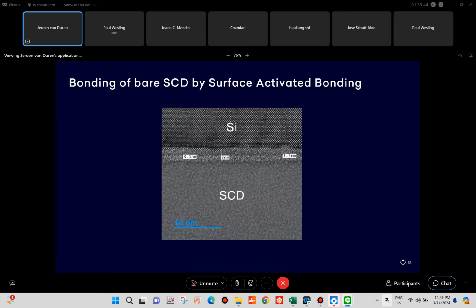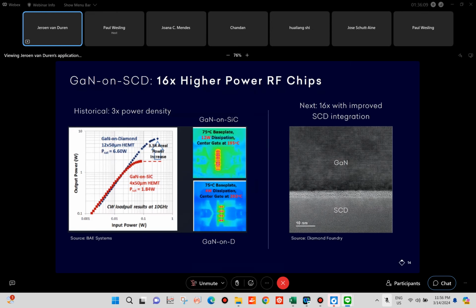For those thinking in TBR values, measured values are like 10 square meter Kelvin per gigawatt. Or for those thinking in different units, it's like 1 times 10 to the minus 4 square centimeter Kelvin per watt. So it's extremely low. That's what is to be expected when you get the diamond so close to the silicon. Now we're working again on diamond with partners. As Joana showed, some nice work from BAE Systems where they got over 3 times the power density for GaN on diamond compared to GaN on silicon carbide, where obviously silicon carbide is already a pretty good substrate to use for RF, which is a substantial power density increase.